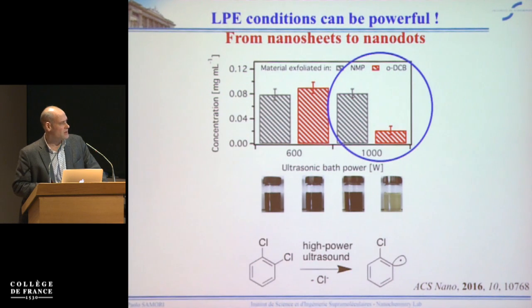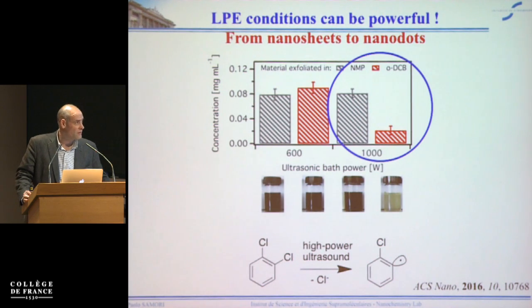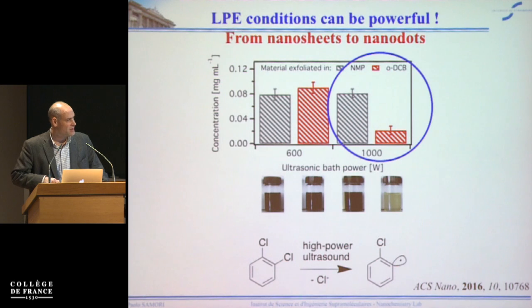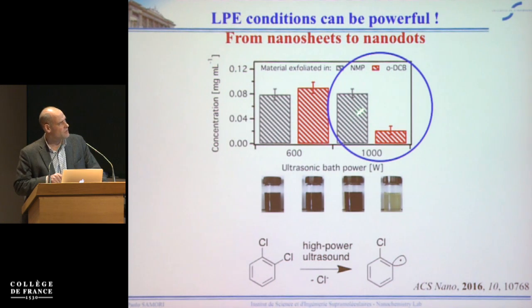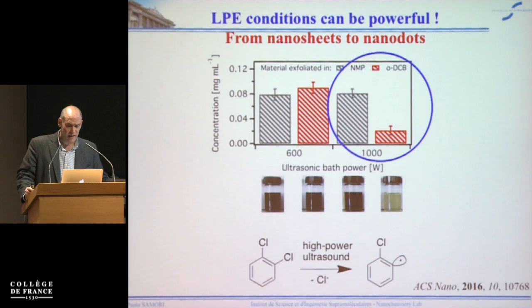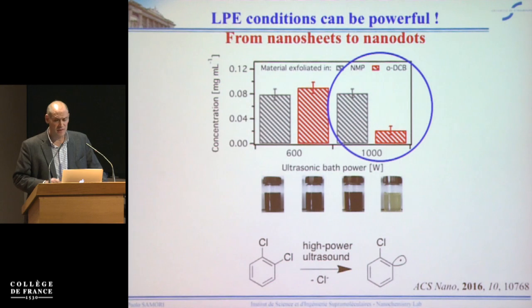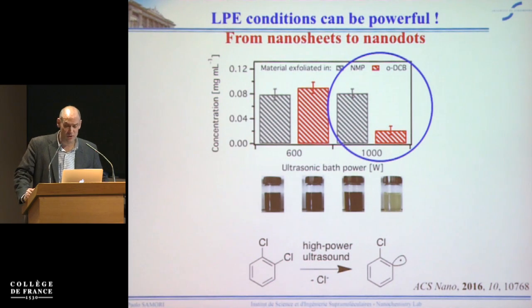And the reason for this is that it is known that when you deal with aromatic molecules that are chlorinated in the presence of ultrasound, they can generate some radical species that are highly reactive. And actually, this was the reason why we obtained a different type of graphene. When we look more closely at this kind of graphene produced here, you can see already that the color is drastically different. While the average size of this kind of graphene here is on the order of 200-300 nanometers in lateral size, here the average size is about 17 nanometers, and they are fluorescent, okay? So I will skip all the characterization of the physical properties, but this is just a simple way to create, let's say, graphene nanodots. So watch out for what solvent you use when you do sonication.